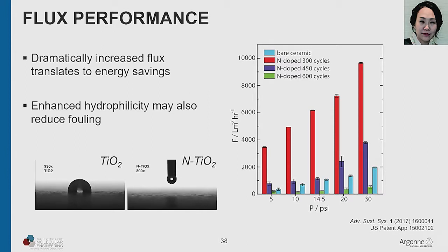So yeah, you don't have a static contact angle because you're dealing with a porous thing and the water is getting absorbed, so you can plot angle over time and then extract curves from that. I'm not showing any of that data here. But obviously, the hydrophilicity has been dramatically increased, which translates into enormous energy savings. Now, the mechanism behind that is light-based, not surprisingly. So you can't take these measurements in the dark. We actually have been trying to figure out how to do that, so if anyone has any ideas, I'd be curious. But we're taking a video here, so we need to have light. And because we've got the dopants, the band gap is now accessible to visible light, that's creating charged species, which we believe are the origin for this super hydrophilicity.